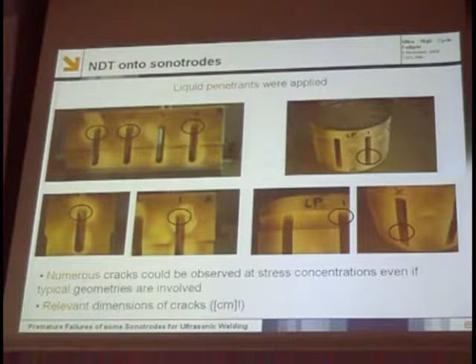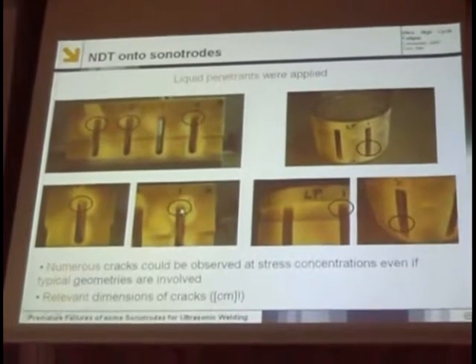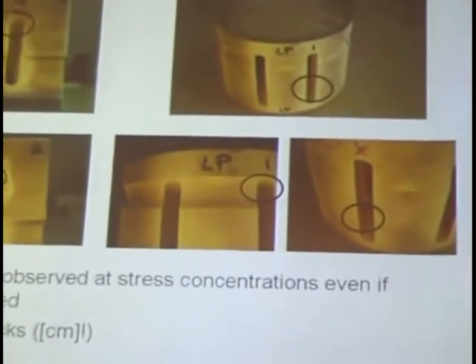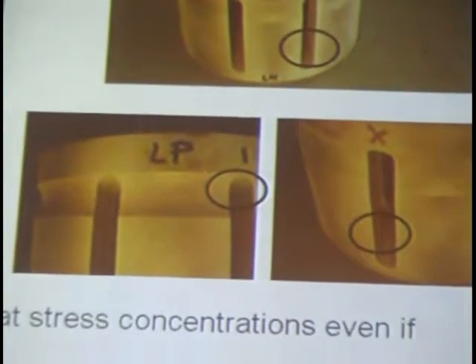From the point of view of non-destructive testing, we applied very simple liquid penetrants on the outside and on the inside of the sonotrodes, and here we have the response of the liquid penetrants. Here we have the red penetrant. It was important that a huge amount of cracks were found in every sonotrode, and these cracks were found at stress concentrations, where we had some geometry discontinuity and the radius between the roof, let's say, and the walls of these sonotrodes.